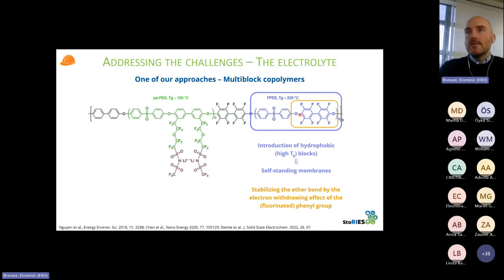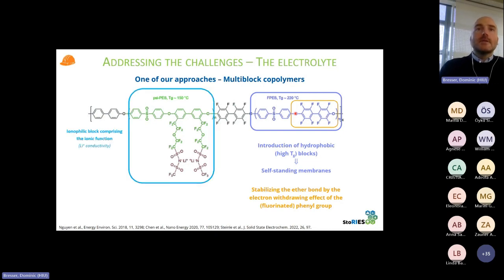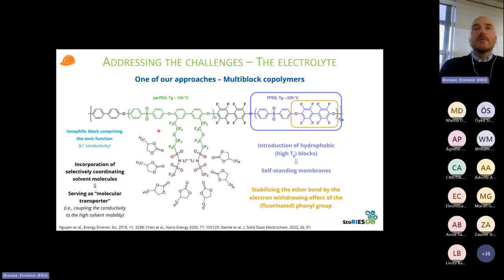We stabilize the ether bond here in these systems, which is the critical point for the oxidation at elevated potentials, by these perfluorinated phenyl groups, basically, that have an electron withdrawing effect on the electrons here in the ether type oxygen, and by this basically stabilize it towards oxidation. And then we have an ionophilic block here in light blue, containing the ionic functions, right? So the anion covalently tethered to the backbone, and then the lithium cation with it, basically that apparently we need for lithium conductivity.